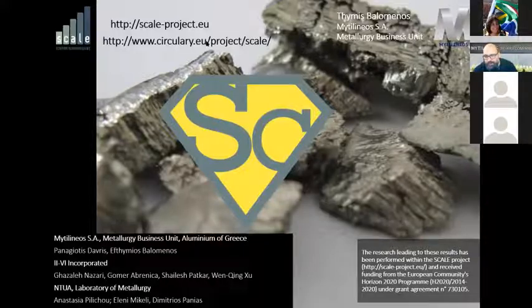And after the ion exchange, in the raffinate you would still have some parts per million, around 10, 12, 15 parts per million of neodymium, yttrium, and so on. Although still, that would be a very poor pregnant liquid solution for rare earth recovery. You would have to probably go again into another ion exchange or other type of technology, even more experimental, to recover the rare earths. I don't think it would be value for money to do that. Okay, thank you very much on that.